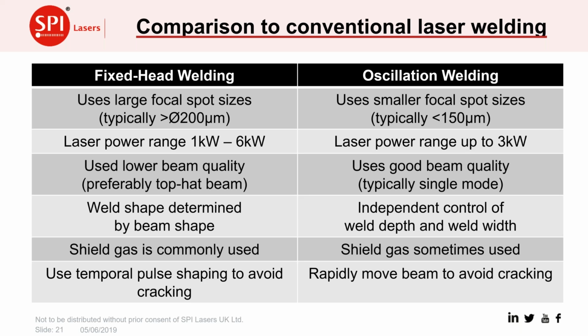And previously, for instance in aluminium welding, there was a way of avoiding the hot cracking by using the pulse shape of the weld to cool it down at the trailing edge of the pulse. But now the rapidly moving beam is able to control the heat input to the process.